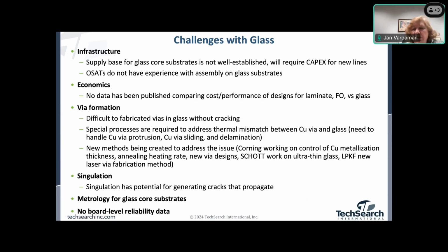In the singulation, this is where we have the problem of cracks that propagate, and there are a number of methods that are being investigated by people like DISCO on how you might singulate this without having the cracking. And then, of course, we need a lot of metrology for these glass core substrates. Very few people have done anything in that area. And there's no board level reliability data. So next slide.